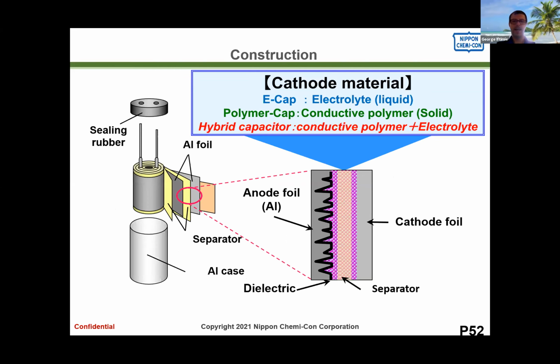Hybrids are not new per se. We've been operating hybrids for well over 5 years. It's something that's always been around. They really are supplementing polymers. So for the very low voltage, up to 16 volts or so, you typically would use a polymer. And for higher voltages than that, you would use a hybrid capacitor. And it's really the best of both worlds a little bit.